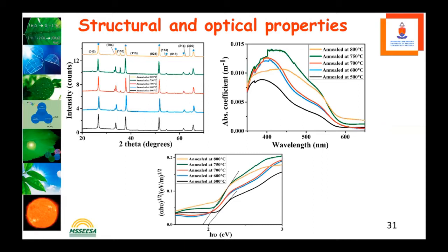And then when the material, I said to the previous caller, the lady who asked the first question, that if we anneal the hematite at 800 degrees Celsius, our crystal nanostructure starts cracking. And that simple mechanical issue, the fact that it has cracked, has produced a defect. And that defect will definitely produce a trap for charges. So charges will be trapped when they arrive at that crack. Therefore, when charges are trapped, we expect the series resistance to go high.